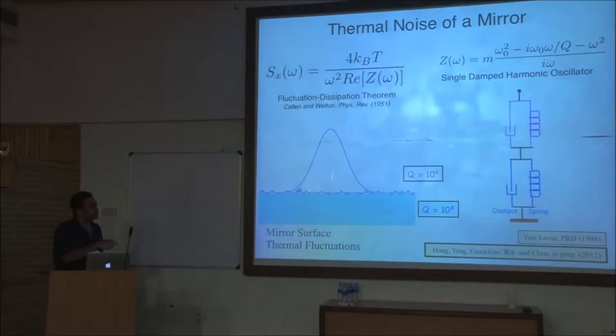So, anyway, you say, I care about the phase shift that this Gaussian beam will feel after it bounces off the surface. And, the conjugate degree of freedom that you drive in order to measure the phase shift of this Gaussian beam is a Gaussian pressure distribution. So, you push on this substrate plus coating with the Gaussian pressure, and you measure the dissipation that you get. And, as it turns out, the, you know, one of the, in fact, the dominant term in figuring out the fluctuation that you get comes from the energy stored and the dissipation in this tiny, tiny surface layer.